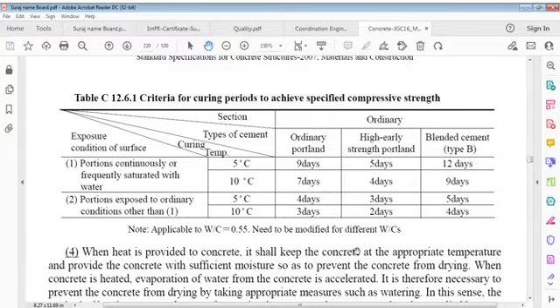That is, for ordinary Portland cement, temperature is 5 and 10, that is 9 days, 7 days. Curing period is 9 days at 5 degrees or 7 days at 10 degrees Celsius. Same way, the other one is 5 and 10: it's 4 days and 3 days. Portions exposed to ordinary conditions versus portions exposed to saturated water. In that case, 9-7, it's 4 and 3, approximately less than half. High early strength is the